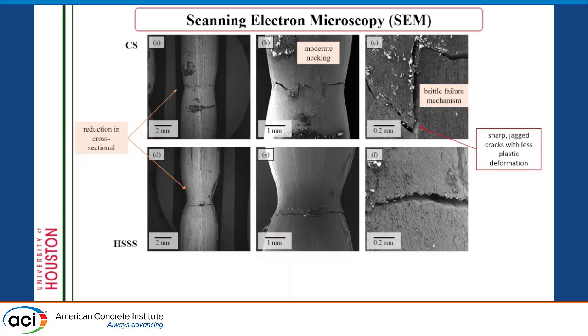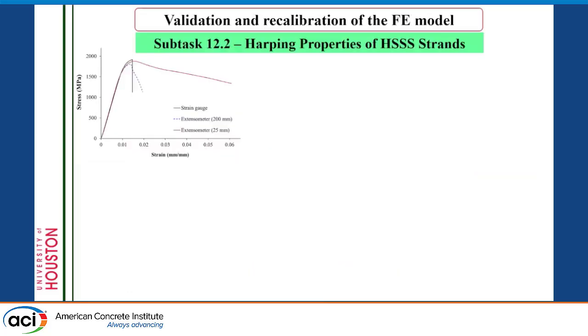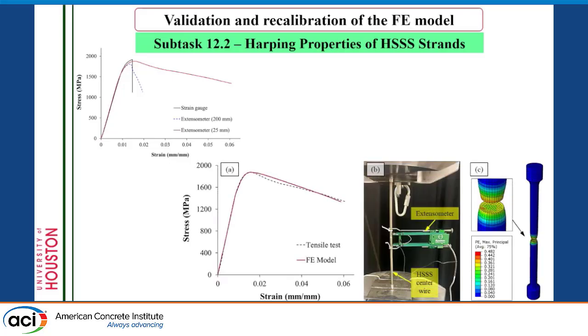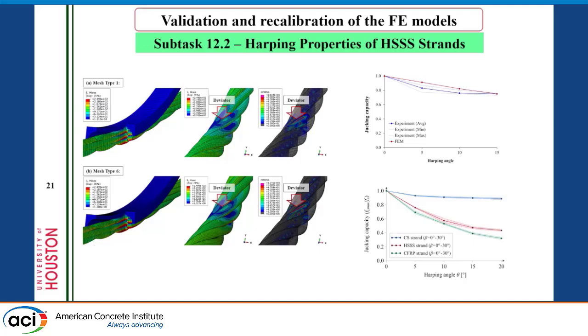And that gives an explanation why in the FEM we got lower results compared to the experimental tests. When we tried to recalibrate, in the FEM usually we use either the extensometer that we have, which is 200 millimeters, or the strain gauges, but the necking or the rupture, where it happened, is where the localized high strain is. So we tried to capture that strain. You can see when we use the 1 inch, I tried to orient the rupture, so I reduced the section a little bit, and after that I did the tensile test so the failure happens within the 1 inch, where I got this high strain softening. And that explains why in the harping we got that kind of results. We recalibrated our FEM modeling, and the ones on the bottom are the blind prediction that we did in the beginning, and the ones on the top are what we got after our recalibration.